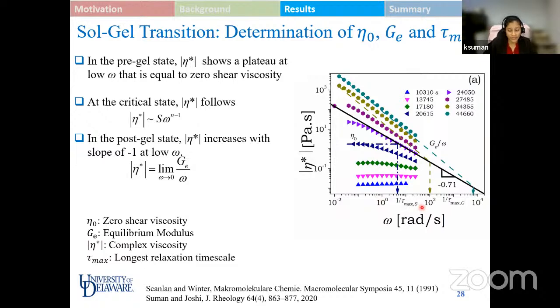Now the scaling laws were proposed for zero shear viscosity and equilibrium modulus. In order to estimate those parameters, we use complex viscosity as a function of frequency. In the pre-gel region, we have the low frequency asymptote, and we can see the complex viscosity achieve a plateau value. This plateau value is nothing but the zero shear viscosity in the pre-gel region. In the post-gel region, the complex viscosity increases with a slope of -1, which is the low frequency asymptote. So we draw the low frequency asymptote in the post-gel region, and with the help of these asymptotes, we estimate the equilibrium modulus. So now we have estimated zero shear viscosity and equilibrium modulus in the pre-gel and the post-gel region.